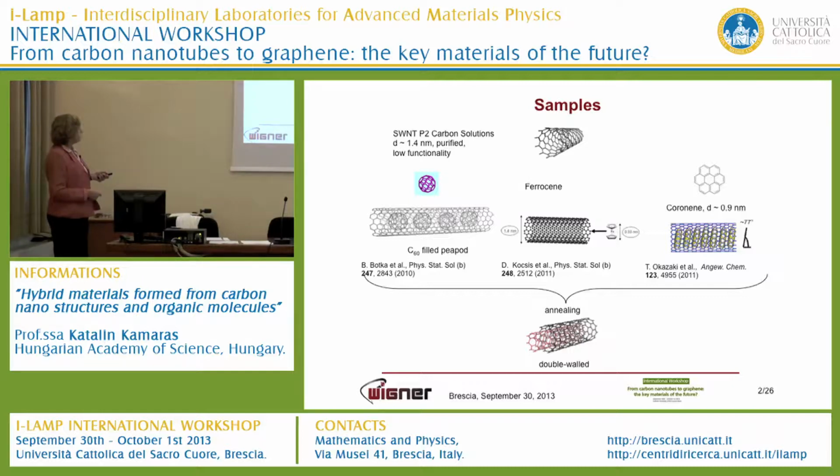But if you have more sensitive samples and you want a lower temperature, you can do a so-called nano extraction from a solution, say with ethanol, any kind of solvent which does not have very strong interaction with the guest molecule, but where the guest molecule has strong interaction with the nanotube. Your nanotube is filled, this interaction is very strong, you have a strong van der Waals interaction here, and then the solution is always saturated, and you fill your whole tube.